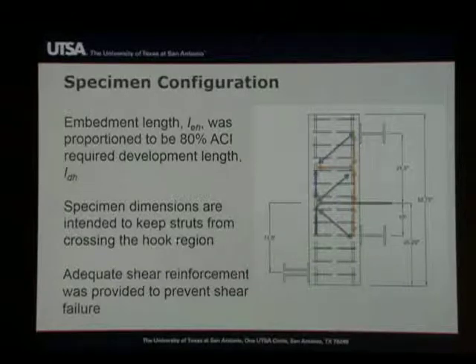What we were trying to do in specimen dimensions, one of the concerns was to make sure that the struts are not too close to the location of the hook, so we don't have a confining effect from this reaction affecting what is happening over there in the area of the hook. And then, of course, we wanted to preclude shear failure, so we use ancillary reinforcement in areas like down here and over here to make sure that we were going to avoid a shear failure.